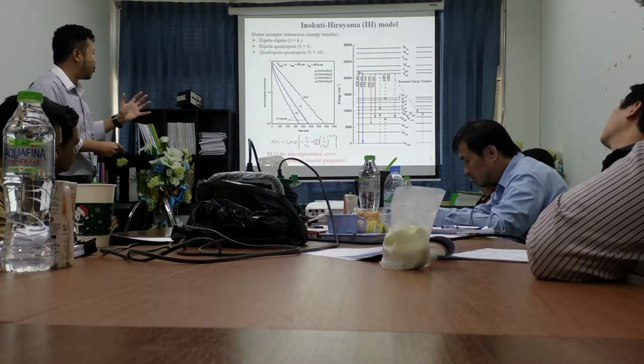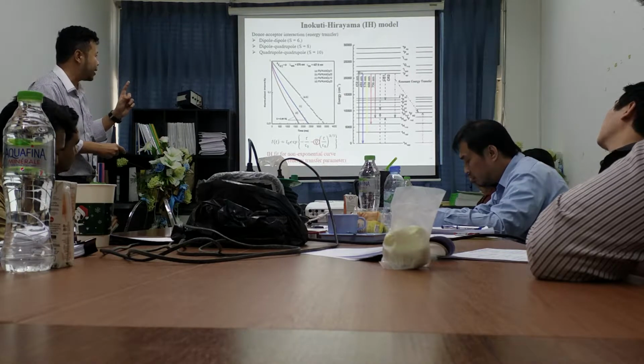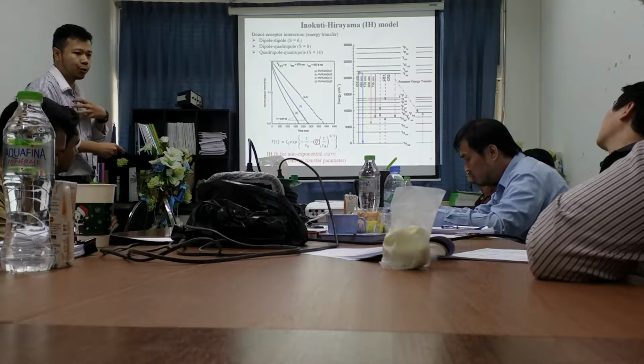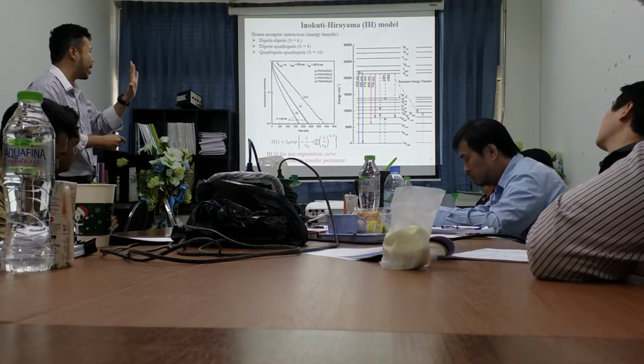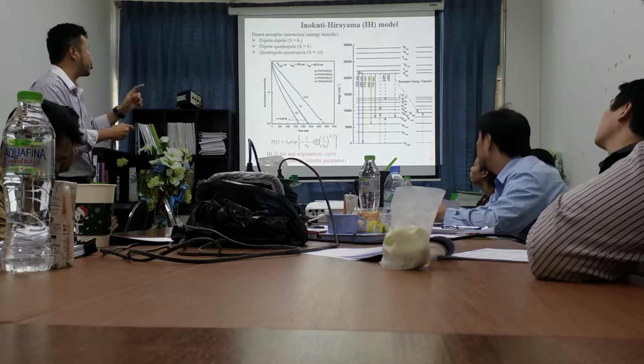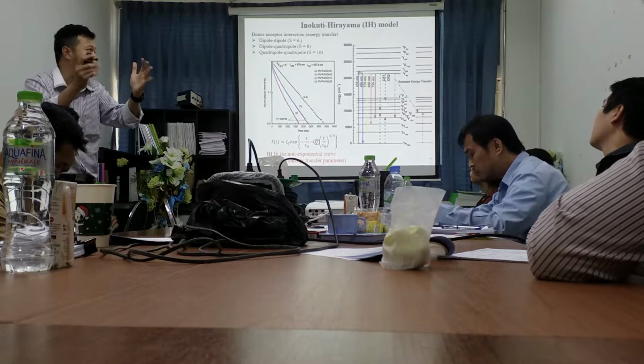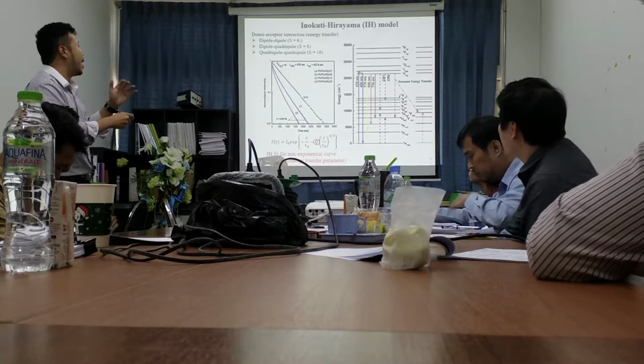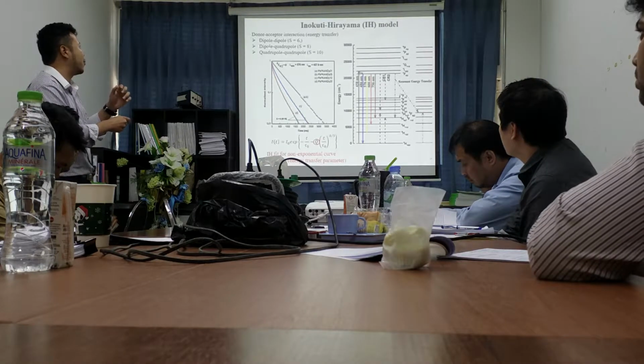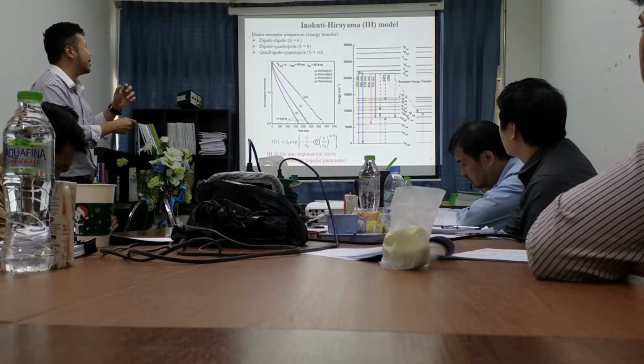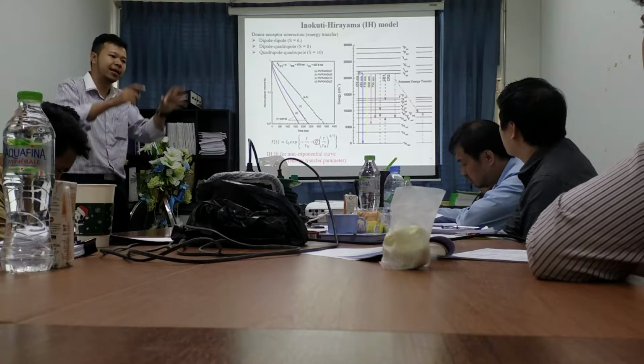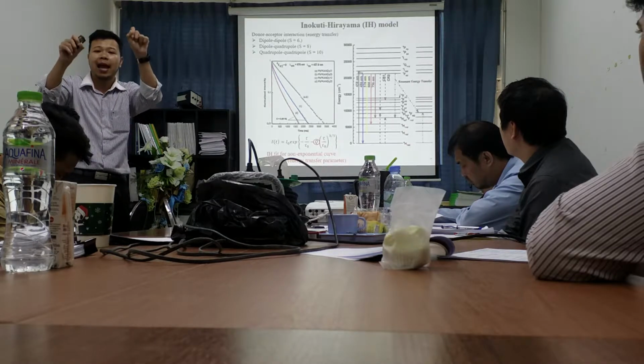And from the fitting, if S equals 6 shows the best fit with our data, that means the energy transfer is the dipole-dipole interaction, and if S is 8 it is dipole-quadrupole interaction, and if S is 10 it means quadrupole-quadrupole interaction. It's the interaction between the lanthanide ions in our glass.